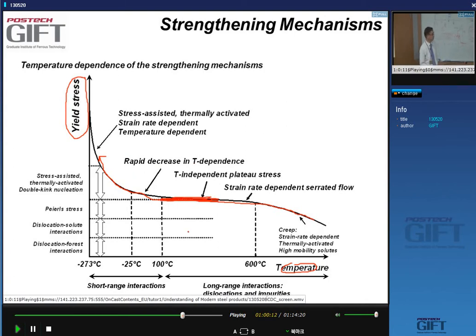well, the strengthening effects that I have added. So I will have the basic lattice strength, which is low for iron. Then I will have my solutes. Solid solution strengthening will contribute to this room temperature strength. And then my dislocations, my strain hardening, will also. So they all contribute to the strength in this plateau.